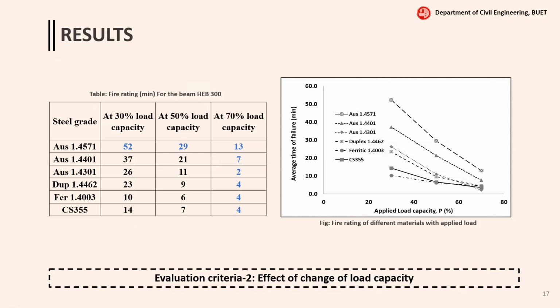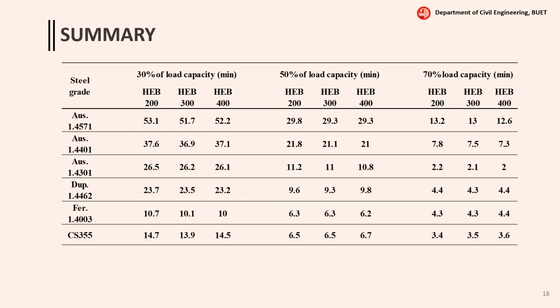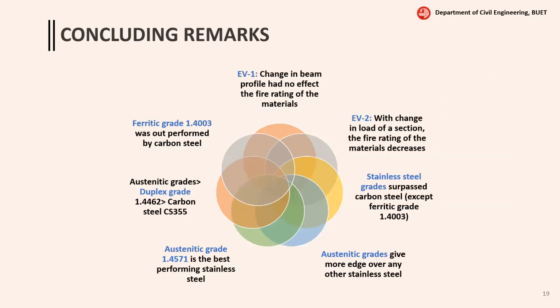Okay, analyzing evaluation criteria 2, that is the effect of loading at the same section, we can see that the fire rating of materials decreases with increase in load, and at higher loading capacity, the difference between stainless steel and carbon steel was almost low. Okay, summary of our results.